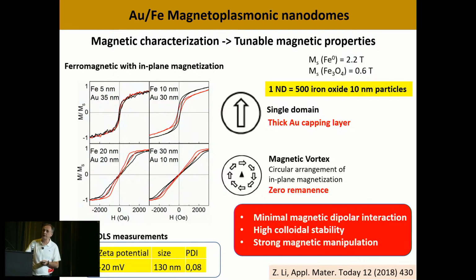And this we can see in the light scattering measurements. You see that the size we get from the light scattering measurement is 130 nanometers. That is 100 nanometers of the polystyrene bead plus the 40 nanometers of the shells. And also we get 20 millivolts zeta potential, meaning that it's a stable colloidal structure. So since we have minimal dipolar interactions, we have a very, very high colloidal stability. But, of course, now we have iron and we have a big particle. So in terms of magnetic signal, one nanodome is about 500 times stronger than a 10 nanometer iron oxide nanoparticle. That means that these nanoparticles are very easily manipulated using magnetic fields.